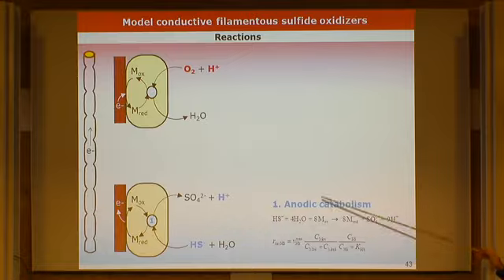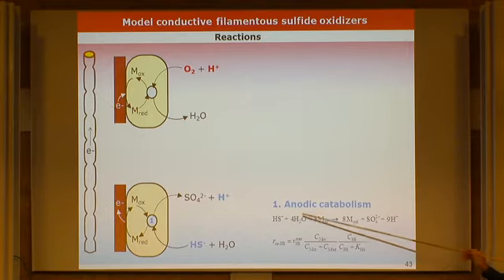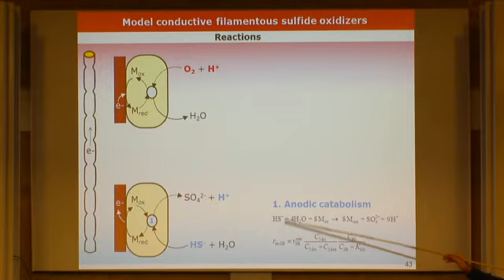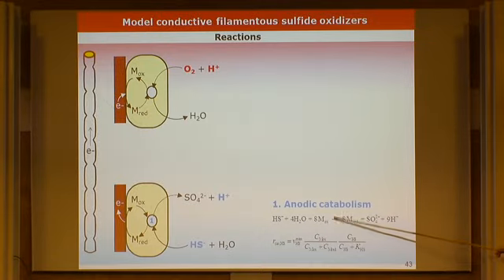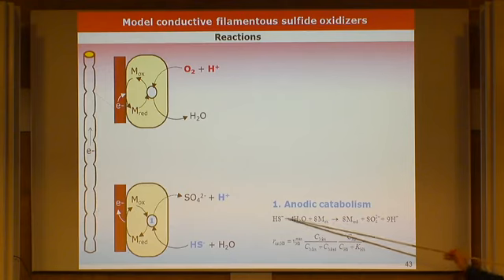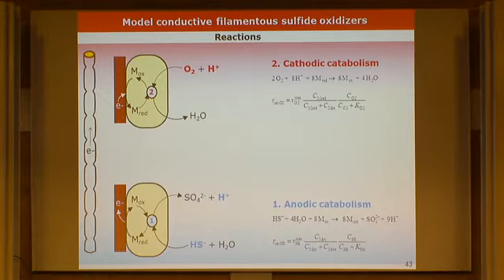So practically we have this anodic catabolism with some stoichiometric equation, electron donor, electron acceptor. The oxidized electron donor is the sulfate, the reduced electron acceptor is the reduced mediator. Eight electrons in this case, from sulfide to sulfate, it's -2 up to +6. And some Michaelis-Menten kinetics, which we thought should be, well, a first approximation.